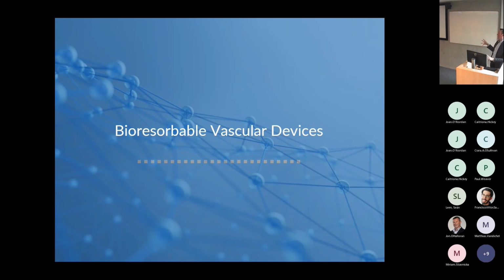What you tend to see is small pits forming, and then they coalesce together. The schematic of that first long narrow pit, we didn't see too much of, and you could see even on the 28-day dog bone, it's degraded all the way around and it's just kind of irregular, but they do tend to coalesce together. It's very interesting. Great, thank you. Time for one more question.